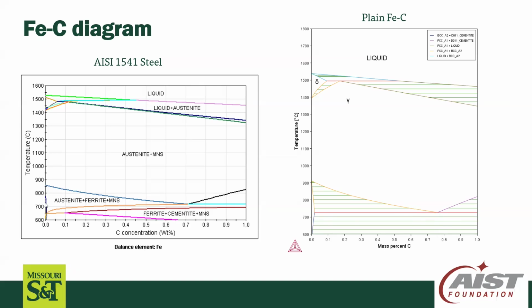But in this case, the temperature seems similar in our alloy, but notice that our eutectoid point has moved to the left when we increase the manganese and the incidentals in our alloy. So it's closer to 0.7, so it has moved to the left. It means that the alloy elements are affecting the eutectoid point. So that's interesting to notice.